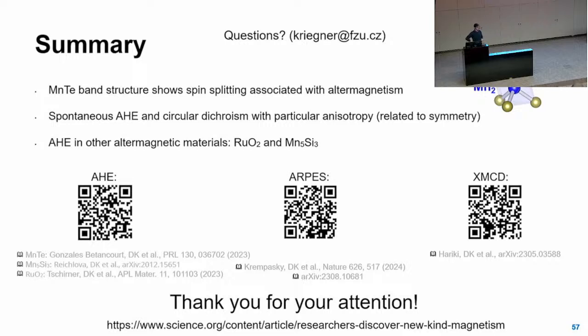Thanks. So they're super useful. I'm not sure about applications, but for our research, definitely. It started all by doing the symmetry analysis, but somehow people started to believe it once they calculated it by DFT. And all the calculations of these band structure diagrams I showed you were all DFT, and without that, I think it would not be possible. How accurate are they? This depends. You saw in this specific zoomed version of it, it was fitting very well. And of course there are some tuning parameters. You might know there is Hubbard U, and you can tune a bit to get to this. But in fact for this manganese telluride, it turned out that it worked very well without a lot of tuning.